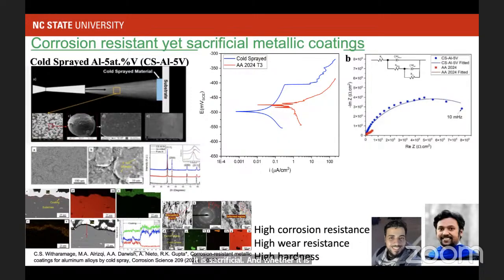And why is that really important? We can take pure aluminum and think about coating it with chromium, with nickel, with other corrosion resistant metals. But what happens is that these corrosion resistant metals have a corrosion potential much higher than the substrate. What does that mean? In case there is a coating breakdown, these corrosion resistant materials will not corrode, they would make the substrate corrode, and that is going to be a huge problem if you want to use these materials in real life. You'll have huge corrosion of the substrate. The situation could be worse than with a material that was uncoated.